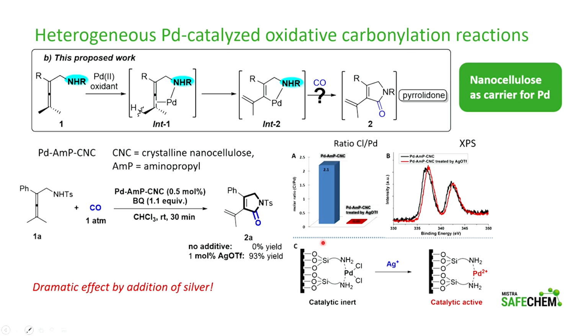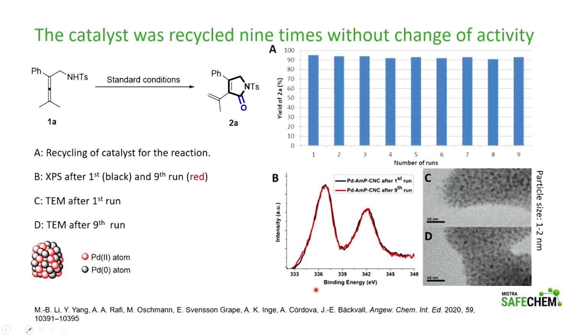And we can see that when you add silver, the ratio of chloro to palladium goes down, and also the XPS is changing from the black to the red. And we believe that the following is happening: silver is removing the chlorides on palladium to give an active cationic palladium catalyst. Now, this catalyst, which works for a number of substrates of this type, can be recycled. You see many times here without any change of activity.